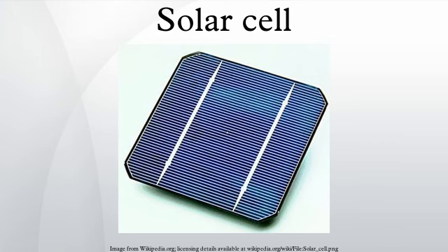A full-area metal contact is made on the back surface, and a grid-like metal contact made up of fine fingers and larger bus bars is screen-printed onto the front surface using a silver paste. The rear contact is formed by screen-printing a metal paste, typically aluminium. Usually this contact covers the entire rear, though some designs employ a grid pattern. The paste is then fired at several hundred degrees Celsius to form metal electrodes in ohmic contact with the silicon. Some companies use an additional electroplating step to increase efficiency.